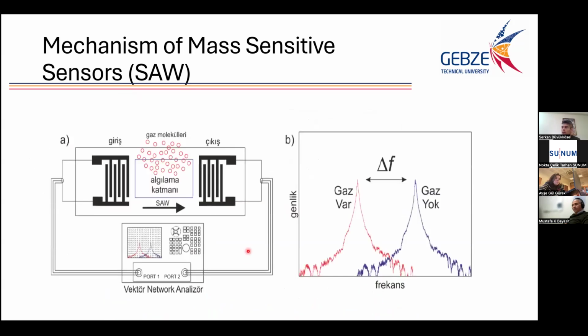In case of surface acoustic waves, the measurement can be done by using this configuration. Here again we have the piezoelectric substrate, generating interdigitated electrodes and receiving interdigitated electrodes, and in between, which is called the acoustic pad, we have a sensing material. When gas molecules are absorbed here, we see a shift in resonance frequency. This can be measured by using a vector network analyzer. Of course, it's not the only way to make the measurements, but in our case, we use the vector network analyzer for now.